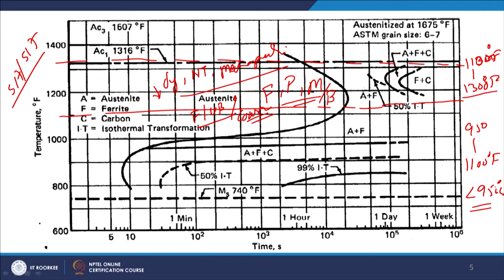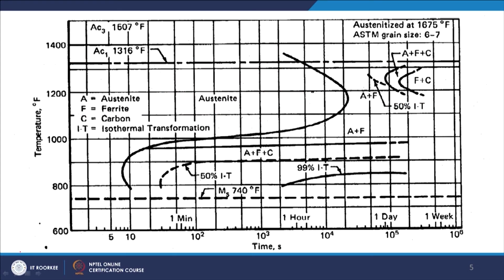If we give the exposure at somewhat lower temperature, there is one important thing that we can see here in addition to this transformation. When the steel is a Q&T steel of 514 or 517 type and is exposed at a high temperature, the time it takes to start the transformation is huge. You can see it is greater than 1 hour or so, or even longer. So, the transformation of austenite into the other phases will start after 1 hour or so.